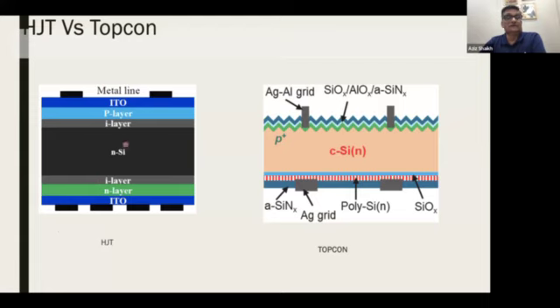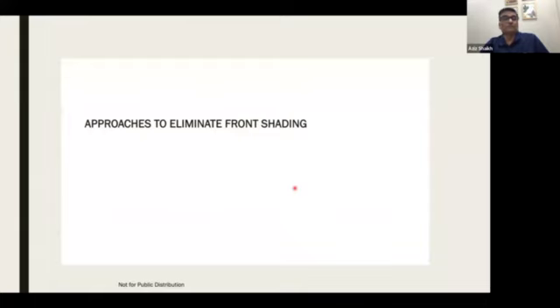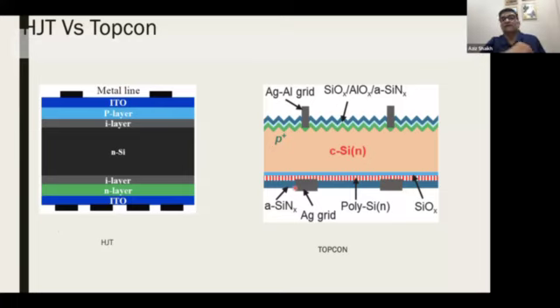Here also you have the same thing in the HJT. You introduce a thin insulator layer. You separate the carrier charge generation from charge collection, and actually you form both sides. I mean, the back surface field, which is the N plus layer, through deposition of hydrogenated amorphous silicon. You also form the same thing on the front side, the PN junction, through deposition, and not through diffusion. It is through the deposition. So with the HJT and the TOPCon cells, now even higher efficiencies are possible. Now, these are successful technologies. Okay, these are dominant.